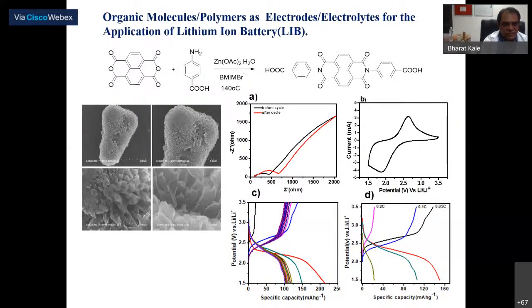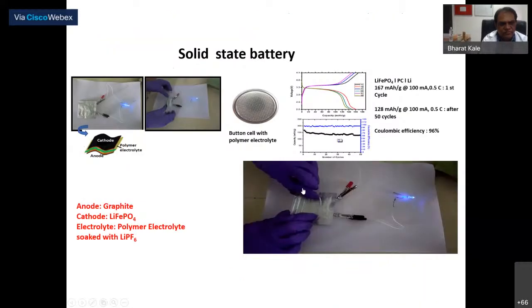Then we have also made some organic electrodes. This is one of the organic electrodes we have. One of our students has fabricated it, and it showed good performance. You can see the specific capacity from 150 milliampere hours per gram to 200 milliampere hours per gram. And we have made 100 cycles; it also gives almost 80 milliampere hours per gram. That is interesting actually, and still we have to refine how we can make their structure. Now this structure is a layer structure, because of that we are getting good capacities.